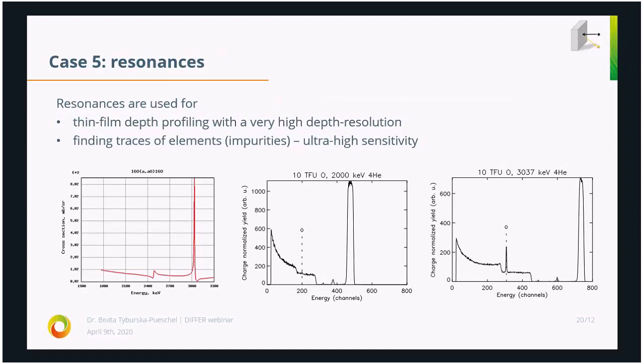Okay, then we also use resonances. What are resonances? Simply, we use the fact that certain cross sections are generally flat and have resonant nuclear reactions, as shown here on the left side. Here you see the cross section for helium on oxygen-16. Generally it is a flat cross section, and then the peak shows up at around 3.1 MeV energy for helium. Those are very narrow, needle-like resonances. You can use them for depth profiling of thin films at a very high depth resolution, in this case even like 20 nanometers if you have some oxygen in silicon.